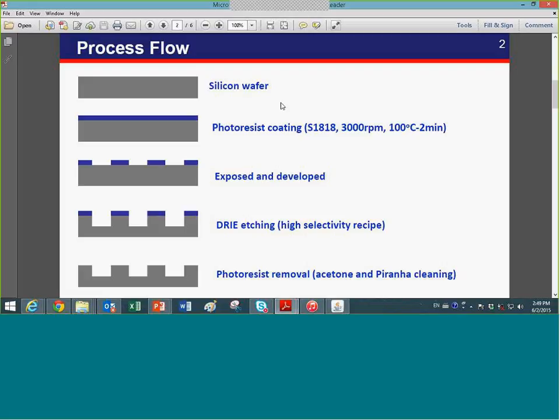The process flow is like this. Starting with the silicon wafer, usually it's a 1 millimeter thick, single side polished silicon wafer, and you use a photoresist. We use a Shipley resist S1818, at 3000 RPM to have a resist thickness of about 2 or 3 micron, and then you pattern it, and then you use this resist as an etch mask in your DRIE, because of the high selectivity of the recipe and the tool. So that 2 micron thick resist allows us to dig really deep through even the 1 millimeter silicon.